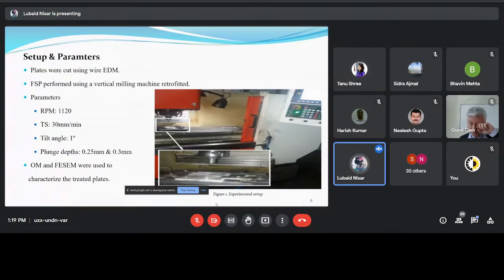It was retrofitted with the help of a suitable tool adapter and work fixture. We can see in this figure the experimental setup, the tool and the plates clamped. The parameters used for carrying out this experimentation were as follows: the rotation speed was set at 1120 RPM, the traverse speed was set at 30 millimeters per minute, and the tilt angle was kept at 1 degree.